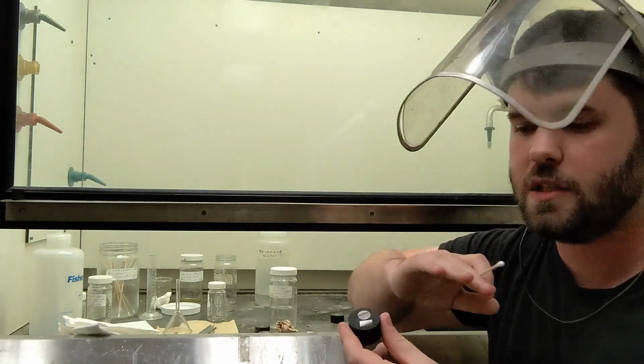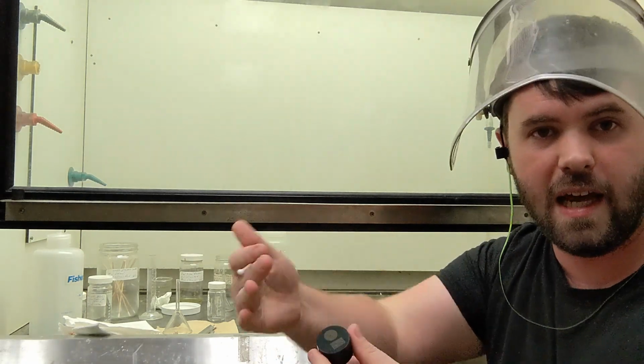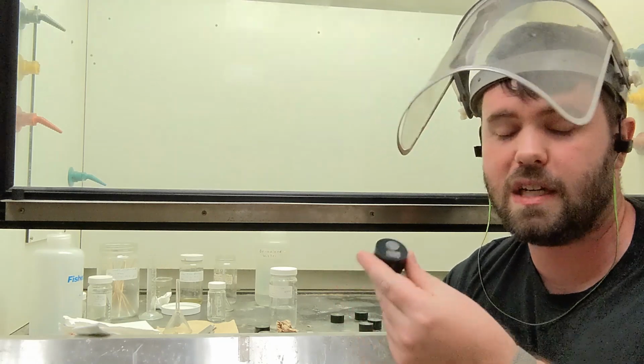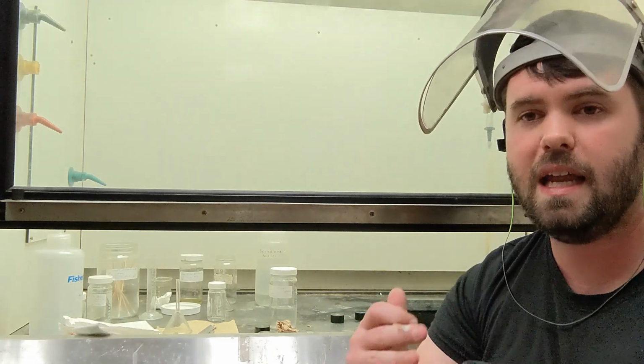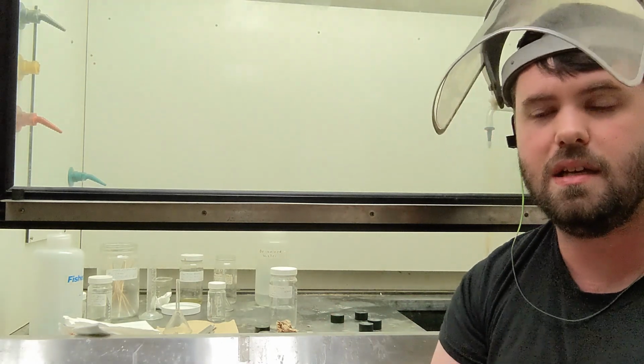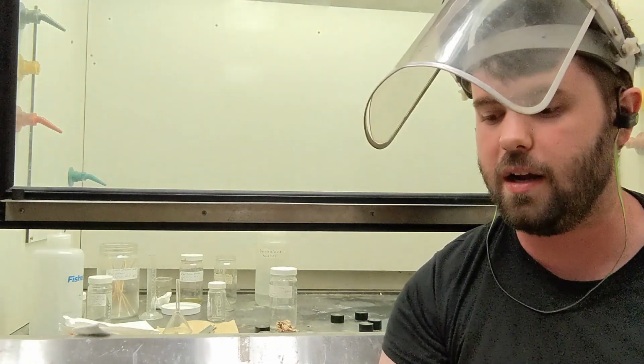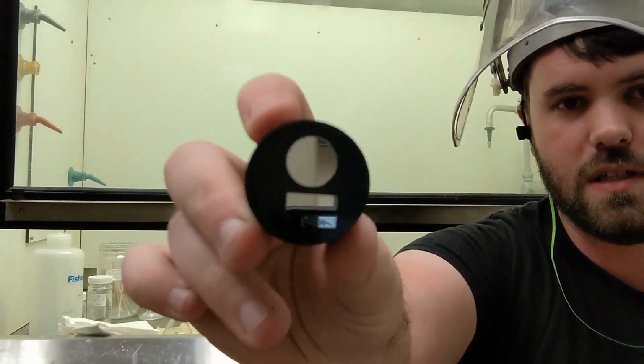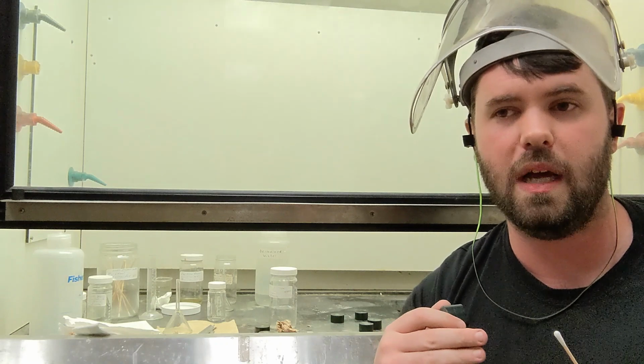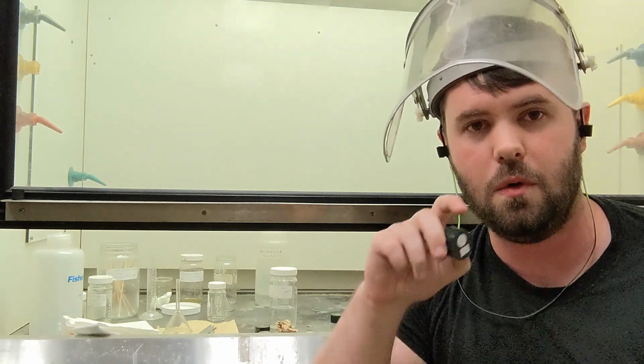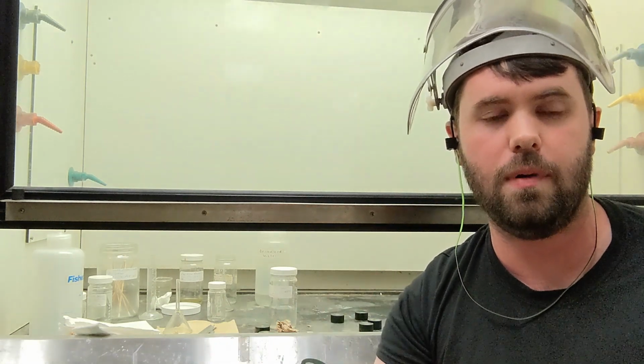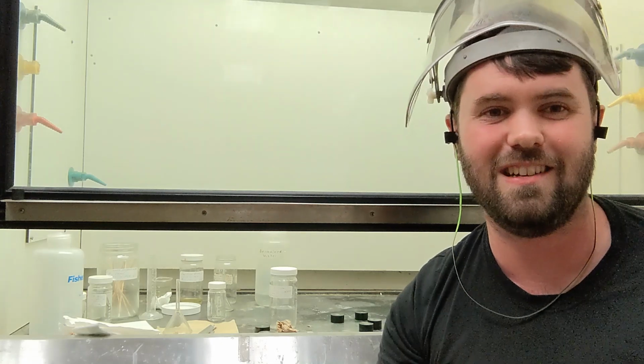And you basically just want to make your sample wet with the etchant. And for steel, it reacts very, very quickly with the Nital. It etches in about 10 seconds. The way to tell the etching is occurring is our polished surface will turn to a kind of cloudy appearance. It will appear like it's not polished anymore, which it's not, because it's etched.